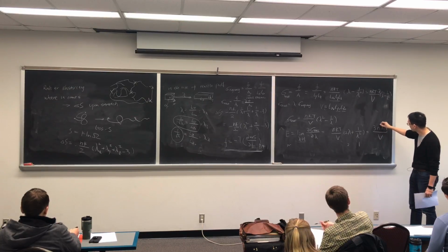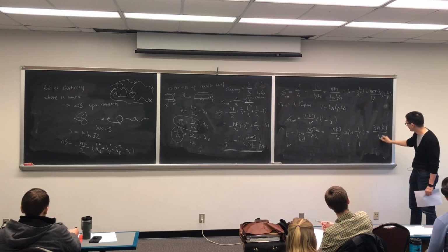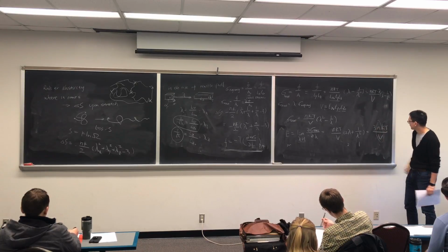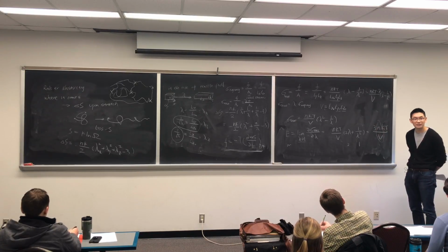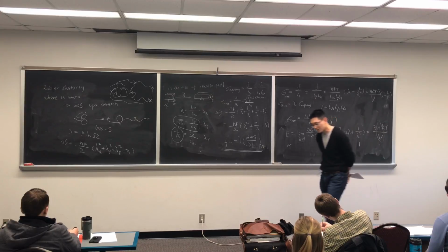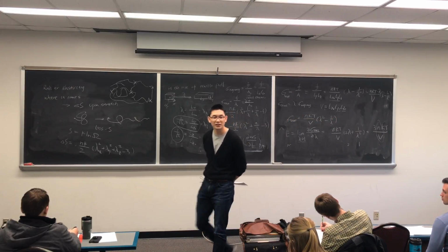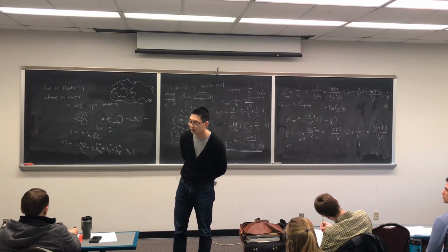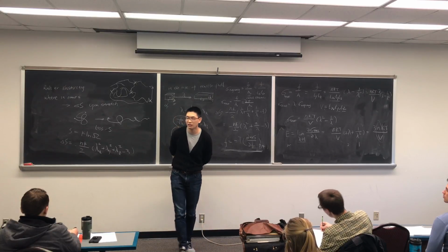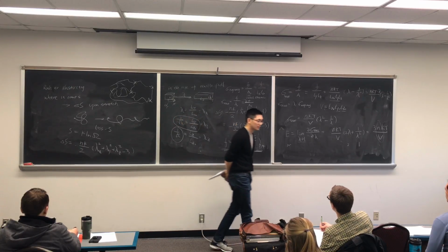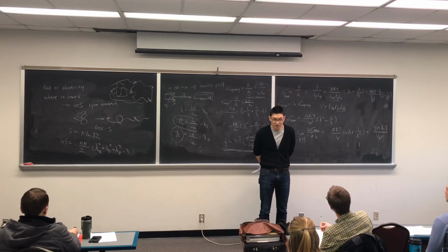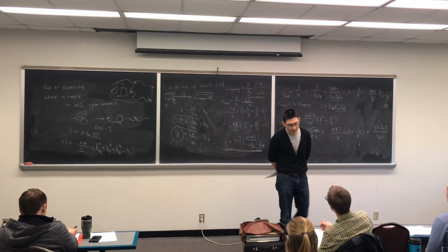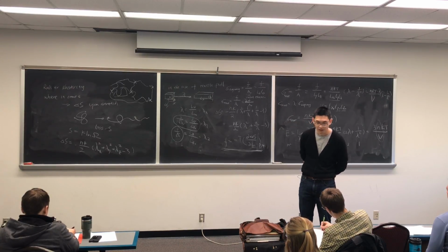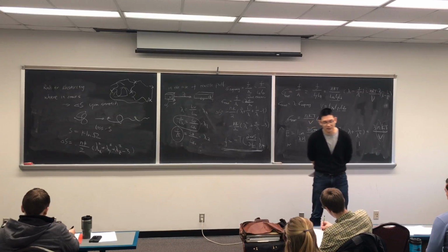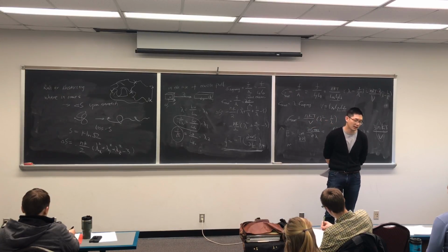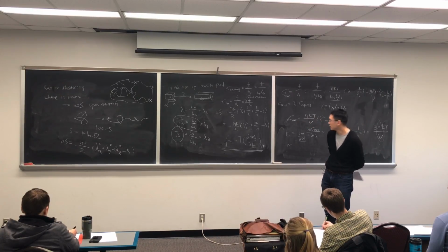The other parameter that is interesting is n divided by V. The n is the number of cross-link points in the system. So n divided by V tells you how heavily you cross-link the material. So like cross-linking density? Yes. So the higher the cross-link density, according to this theory, the higher the modulus you would have.